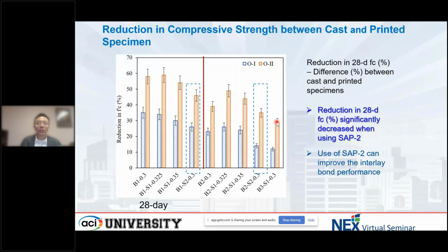But how about the compressive strength of the printed specimen? We compare the compressive strength between the cast and printed specimens. We calculate the reduction as a percentage here, and we can see from this figure the reduction of the compressive strength is quite high for the reference mixture. The blue column means orientation 1, the orange column means orientation 2, and for orientation 2 it comes up to around 58% reduction of compressive strength for binder 1, and this is really a lot. It means the strength of the cast specimen is around 6,000 psi, but we can only get 3,000 psi for the printed sample. Why did it happen? Because we got a very poor bond strength and bond performance, and also a bad surface quality.